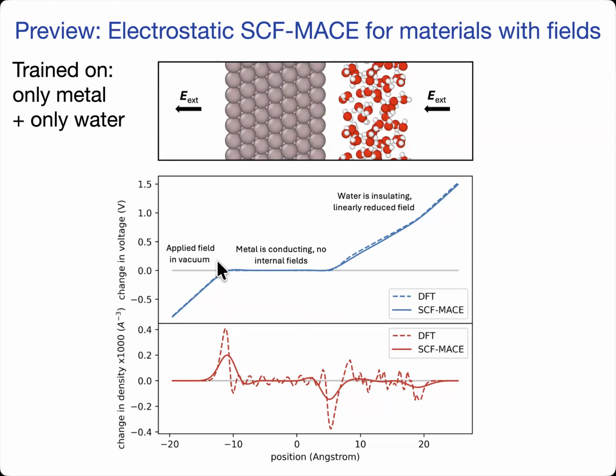So you see the electric field here, the metal is conducting, so no field, and then you see the reduced field in the water, where the electrons polarize a little bit. You have a dielectric constant of 1.8. So you get a reduced slope before you get back to the full slope of the full electric field in the vacuum. And what I'm showing you here is the charge density.